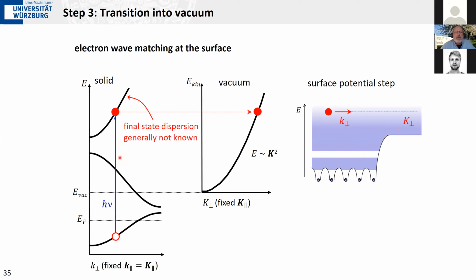I excite my electron to this state here. It has a certain energy and a certain small K perp. And then it goes to the surface and then turns into a free electron wave. But a free electron wave has a parabolic dispersion. We keep the energy here. The total energy doesn't change as we go through the surface. The kinetic energy changes, but not the total energy.